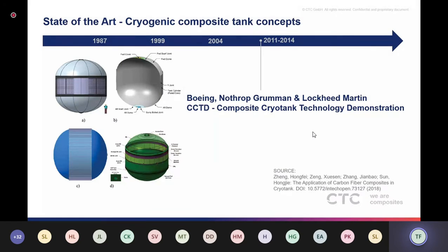A next tank was produced from 2011 to 2014. In the CCTD program, Boeing, Northrop Grumman, and Lockheed Martin all submitted designs for a liquid hydrogen tank made of composite materials, and the design by Boeing was chosen, and the tank was produced. This was made with toughened out-of-autoclave prepreg, also with thin plies to prevent microcracking, and a vacuum insulation around the tank. It was found in testing that the thin plies prevented the microcracking, but the permeability was still too high because the porosity of the material, due to the out-of-autoclave manufacturing, allowed too much permeation.